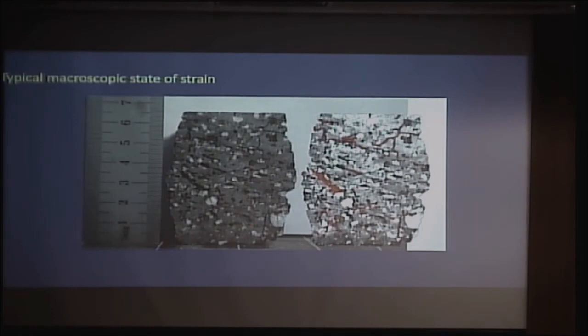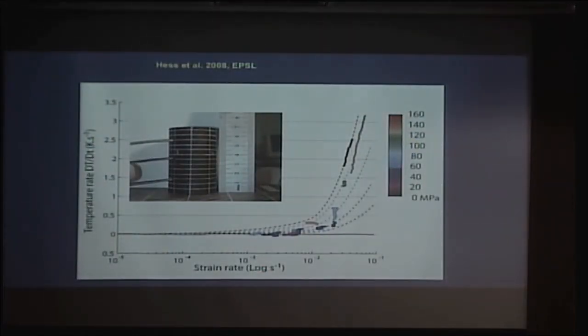beautiful dome lavas. You see we have to use pretty big samples in order to get anything like a characteristic heterogeneity of the sample in the experiment. It's tricky. Here, the scaling is the distance between crystals, the size of the crystals. That's the critical scaling in this material. So we don't have to worry about kilometer-size scaling for using these results. A lot of people know that scaling is important, but a lot of people misunderstand what scaling is relevant to a particular experiment. This is not fluid dynamics. So here you see the temperature beginning to run away.